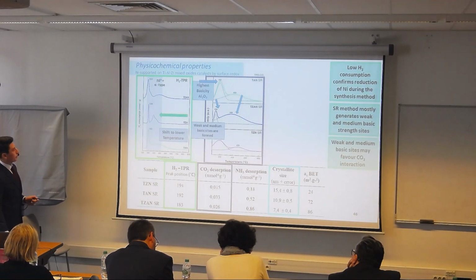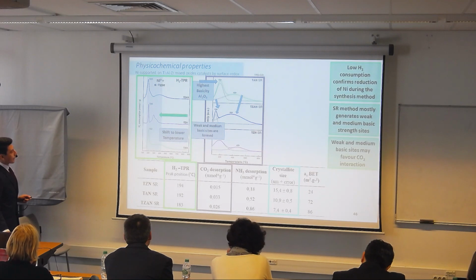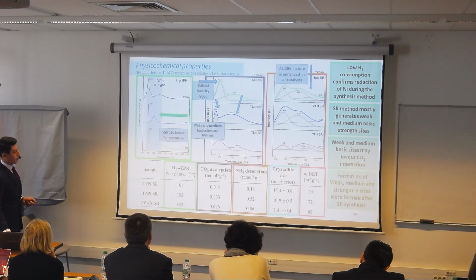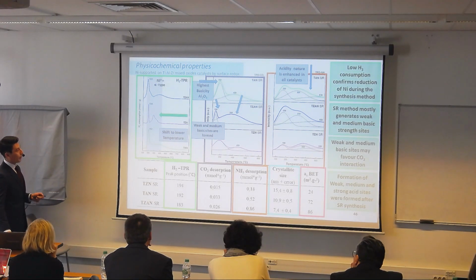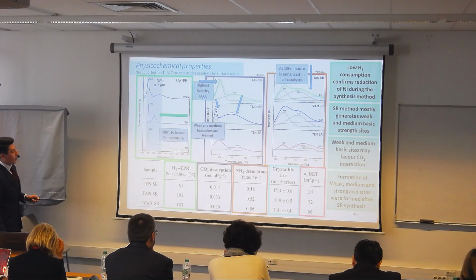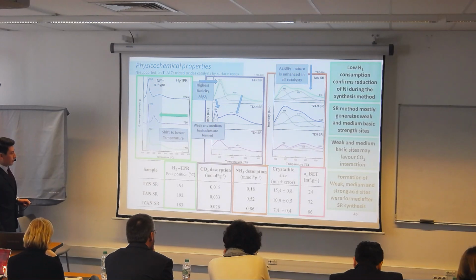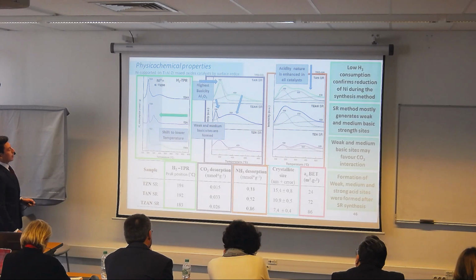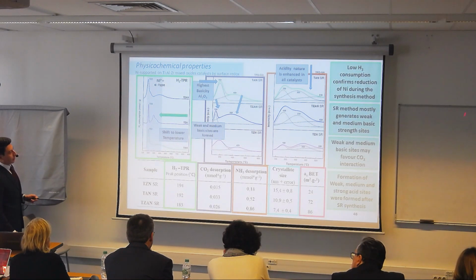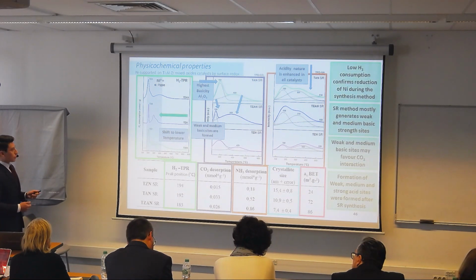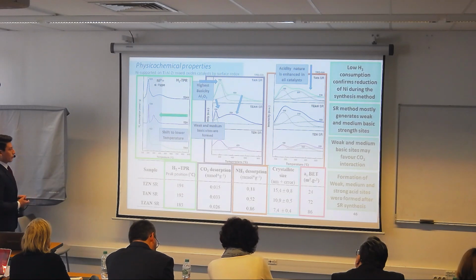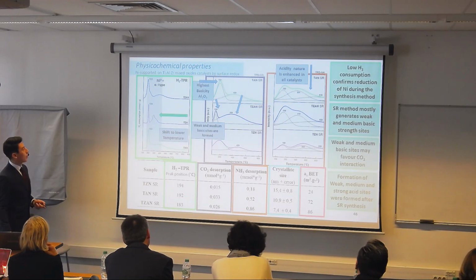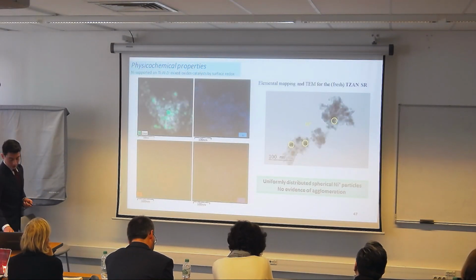About the acidity and basicity, we have a high basicity when we are using alumina, and in all of them we are producing weak and medium basic sites. About the acidity, we can see that in all of them it is increased compared to the others. However, the area is reduced, but the main factor is that the acidity is higher compared to all the materials that we prepared before. So this surface redox method mostly generates a very good formation of weak, medium and strong acid sites that are promoting the activation of methane.